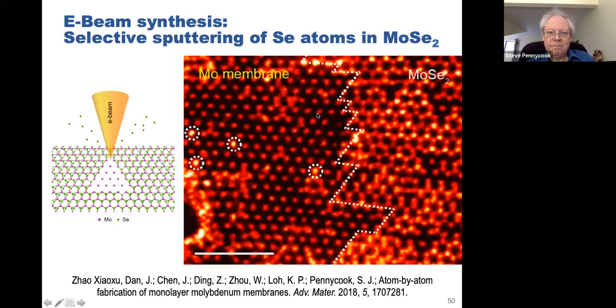He figured out that the electron beam can sputter selenium selectively. He was able to fabricate a molybdenum membrane. You can see this is just molybdenum. All the seleniums have been sputtered away, but this is reasonably stable. And it maintains the hexagonal structure that it had in its parent.